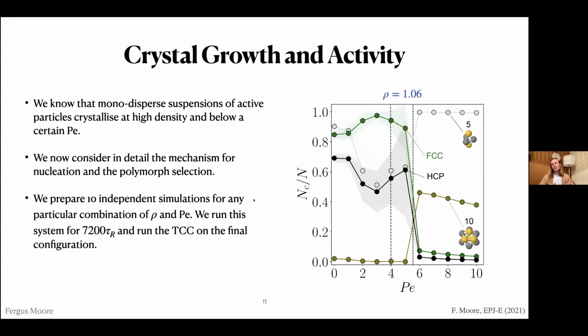And so if we're looking at structure, and we're going to be applying this TCC, one thing we can do is at a particular density, we can run the system for a long time at different Peclet numbers and then look at the structure that arises after a long time as it asymptotically arrives at a final state. So we have the fraction of these different structures. We have the two crystals, FCC and HCP, in green and black. And then I've also included these liquid structures that are very prominent. One thing to note, since the TCC is a cluster-based model, particles can belong to more than one cluster, so don't expect these numbers to sum to 1.